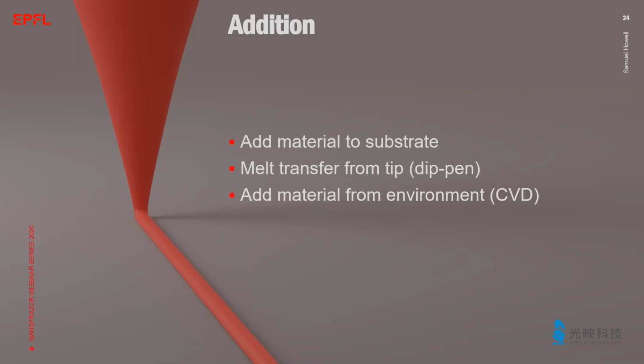And when the tip is heated and brought into contact with the substrate, a flux of the melt is established across the tip sample contact. And then scanning the tip over the substrate creates arbitrary patterns that can be used for pattern transfer with standard lithography techniques such as dry etching. Basically similar techniques as discussed for the removal.